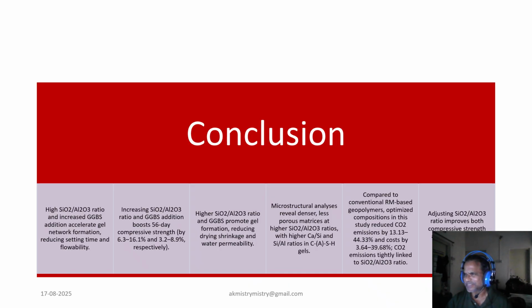So, in conclusion, this study shows that increasing the silica-alumina ratio and incorporating more GGBS accelerate gel network formation, improving strength and reducing setting time and flowability. Enhanced formation of hydration gels also reduces drying shrinkage and water permeability. Microstructural densification with increased calcium-to-silica and silicon-to-aluminum ratio further strengthens the material. Optimized red mud-based geopolymers demonstrate substantially reduced CO2 emission and lower cost, supporting sustainable building material development.